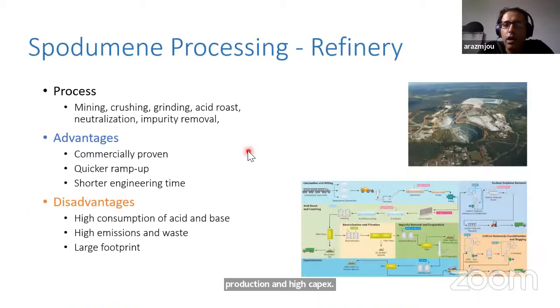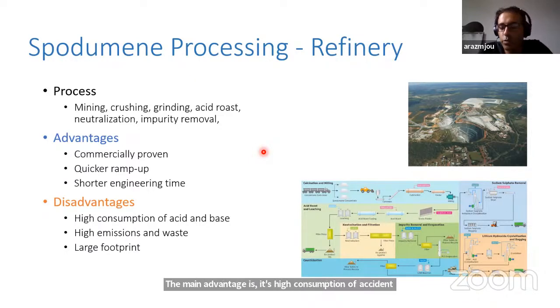This is a typical spodumene processing. The process usually comes with the mining, crushing, grinding, acid roasting, and impurity removal. The main advantages are that it is commercially proven, quick to ramp up, and requires shortened engineering time. The main disadvantages are its high consumption of acid and base, high emissions, and large footprint.